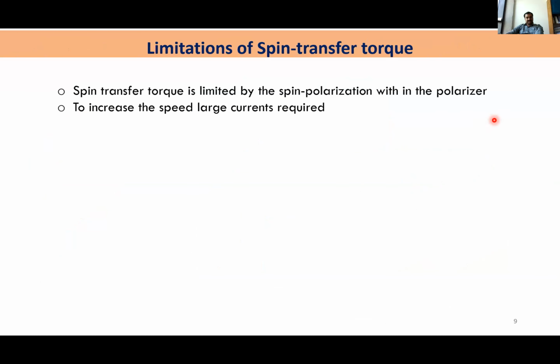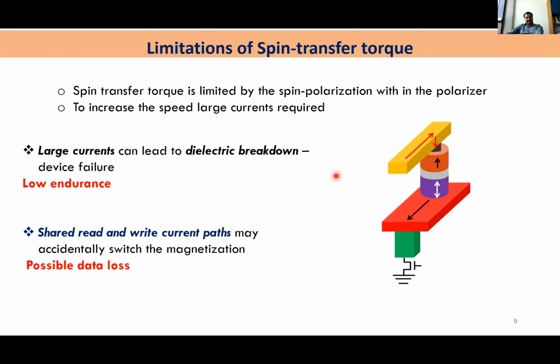However, there are still some issues with spin transfer torque based magnetization switching. To increase the speed of the device, you need to apply larger current pulses, and you have a tunnel barrier which can cause dielectric breakdown. So we are compromising on endurance. There will be low endurance if you apply higher currents. Also, as you can feel, there are shared read and write paths, so there is always a possibility of accidental switching. So we are also compromising on data loss. Basically we should not apply a very high current through this tunnel barrier. So we need to decouple the read and write paths.